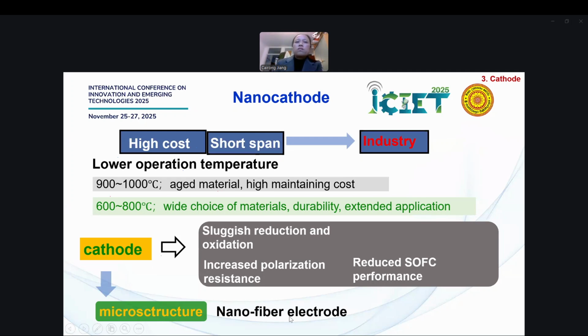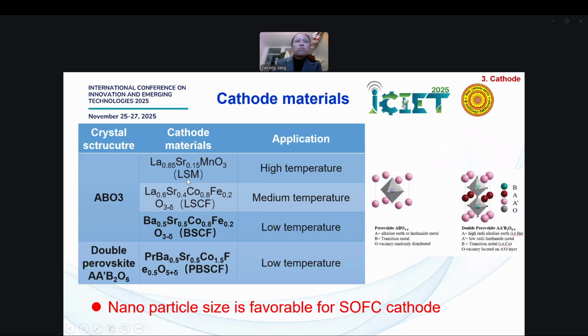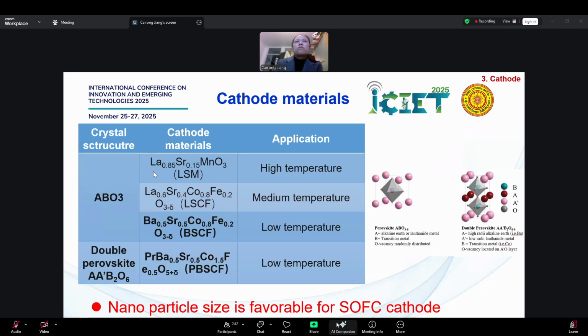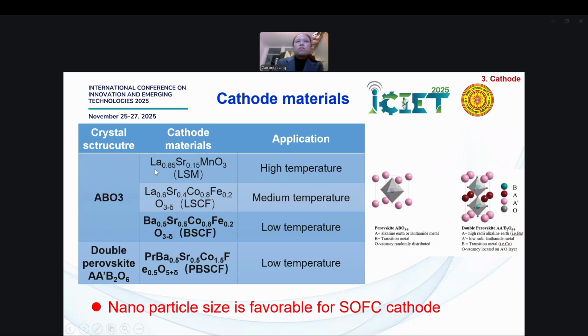A nanocathode is a choice. One of them is nanofiber. We have gone through a few materials we can choose for all sorts of cathode materials. They are all based on the perovskite ABO3 structure. It can be lanthanum strontium manganite, which is usually used for high temperature. Another good choice is lanthanum strontium cobalt iron, which is for medium temperature. But if we prepare a good powder, it can be used for quite low temperatures, like the other two materials, barium strontium cobalt iron. So all sorts of designs can be used. For the barium one, there's a bit of risk of being affected in carbon dioxide. It easily reacts with it to produce barium carbonate.